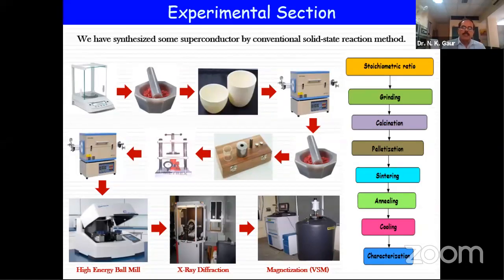Here, I have shown you there are a number of techniques by which we can grow the thick and thin film of superconductor. Here, I have shown you the conventional solid state reaction method by which we can grow the bulk material. This is the flow chart for the solid state reaction method, in which we take the stoichiometric ratio and weigh it, and then second is grinding. So we grind it up to the atomic level so that they mix up to the atomic level. We grind it for a few hours, and then the mixture is put in the crucible and finally placed in the furnace. The temperature depends on the material, somewhere around 800 to 1400 degrees centigrade, depending on the compound.